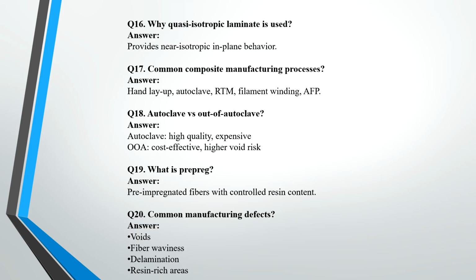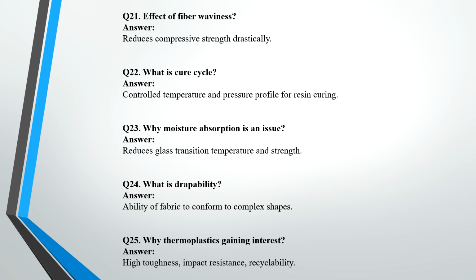And what are the common defects we observe in composites? One is void, fiber waviness, delamination, and resin rich areas. What is the effect of fiber waviness? It reduces the compressive strength drastically. What is the cure cycle? It controls the temperature and pressure profile for the resin curing. So the next is, why is moisture absorption an issue? It's because it reduces the glass transition temperature and the strength. What is drapability? It's the ability of the fiber to conform to complex shapes.